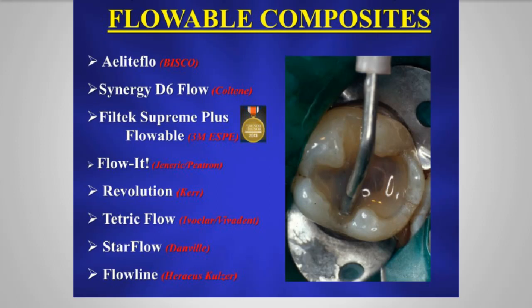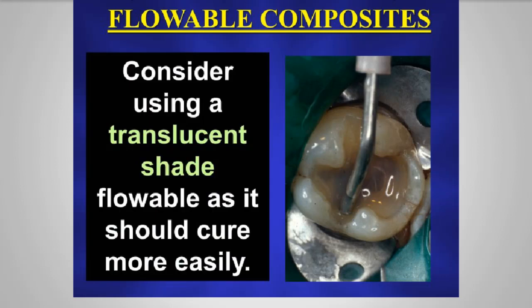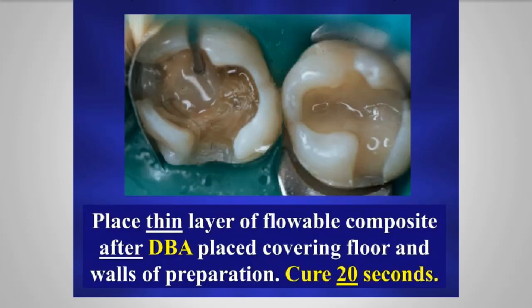And if you're going to use a flowable, it should be placed in a thin layer, after the dentin bonding agent is placed, covering the floor and walls of the preparation. I recommend you cure these for a minimum of 20 seconds. I'm not a big believer in rapid curing. I don't believe in a 5-second cure. I don't care what light you're using. And I don't think we'll have time to get into that, but there's a lot of good reasons why I don't think you should be using high-intensity lights for short cure times.